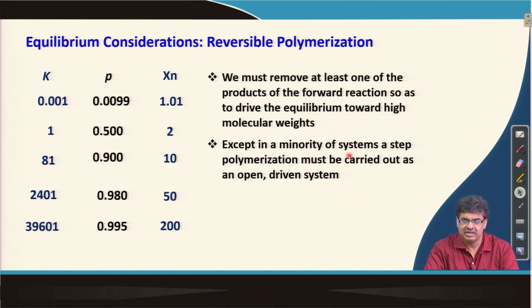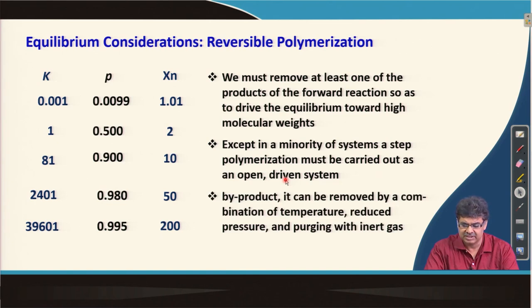So, except in a minority of systems, a step polymerization must be carried out as an open and driven system. Open means we drive out one of the products of polymerization, and in this case we generally prefer to remove the small molecule because that is easier to remove from the reaction mixture compared to the polymer.